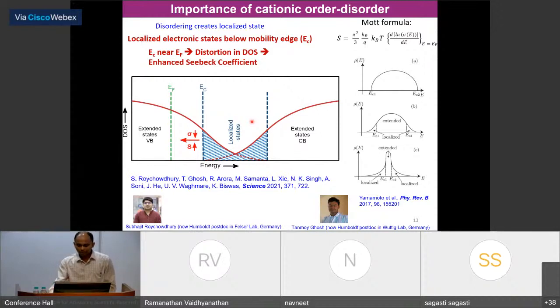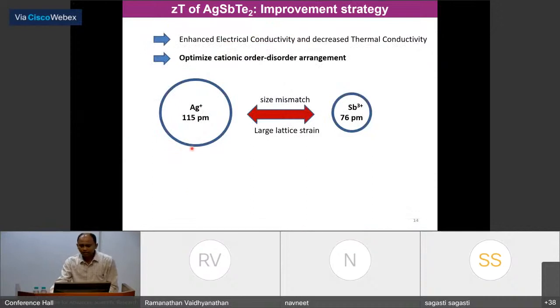So in order to do that, we worked on this AgSbTe2 compound. As I told you, the puzzle in this compound is the disordering of silver and antimony, because both sit in the octahedral position. Silver has a different charge compared to antimony, as well as a different size. This is one of the main reasons for the disordering of this compound. So we are looking at how to make this cation ordered, so that we can play with the delocalization of the electronic states. That is the main goal.